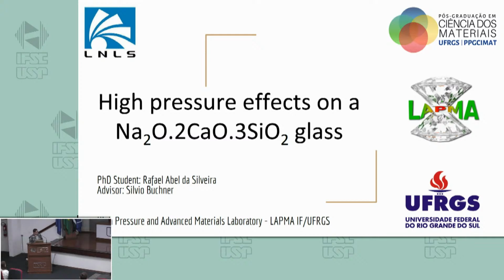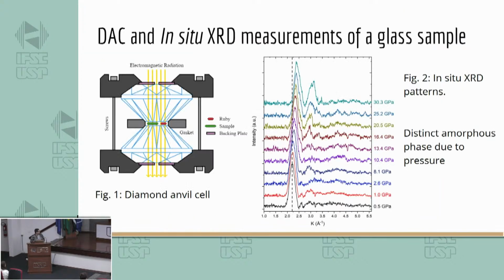So, hello everyone. I am Rafael Abel da Silveira. I study at the Federal University of Rio Grande do Sul with Professor Silvio Buchner. I mainly focus on the effects of high pressure on glass. Something we did lately was to use a diamond anvil cell at the synchrotron laboratory here in Brazil, where we used a glass. In a diamond anvil cell, you put the sample between two diamonds and basically press them, so you can have in situ measurements.